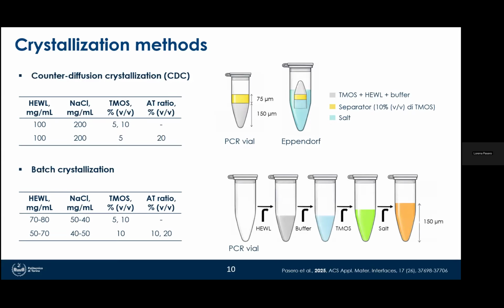And in this case, in a PCR vial, we can add different solutions based on protein, of course, the buffer, then the TMOS, which creates the gel, and the precipitant, and they are progressively mixed to create an environment where the protein and the salts are in contact. Also here, we varied the concentration of TMOS used to obtain the gelation, and so the formation of gel. And we also introduced a new parameter, which is the additive to TMOS ratio, AT ratio, which was varied between 10 and 20 to also assess the effect of the concentration of the additive. And also we varied the protein and salt concentration to vary the supersaturation of the system.